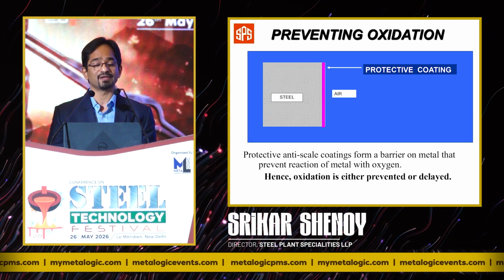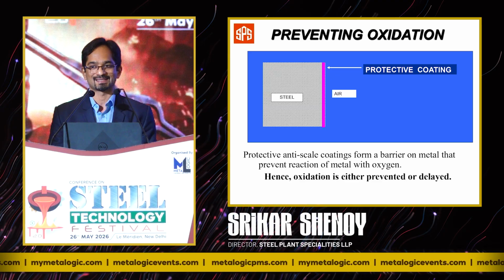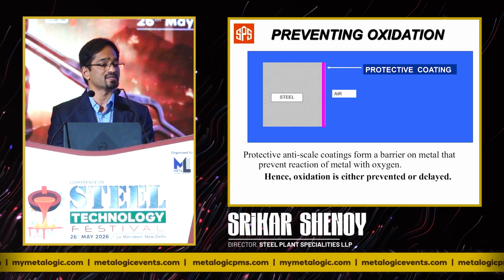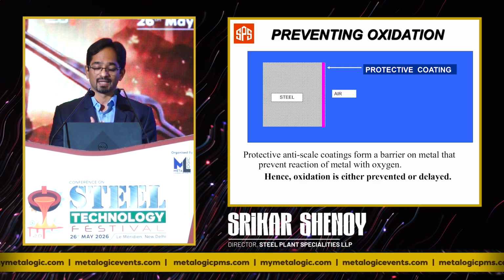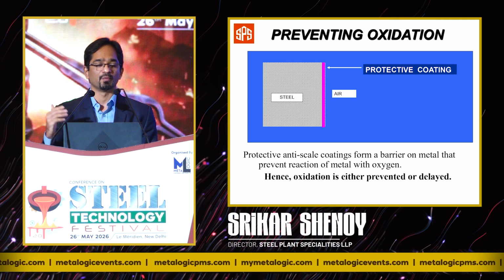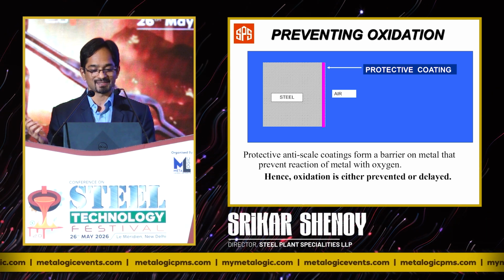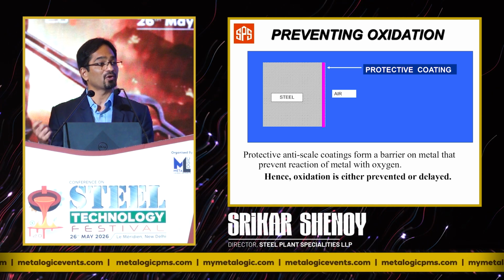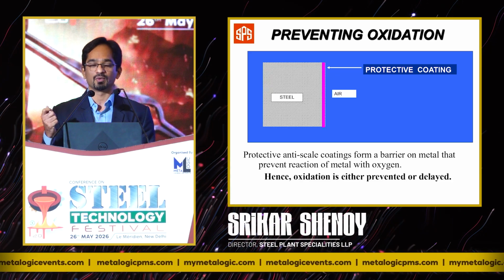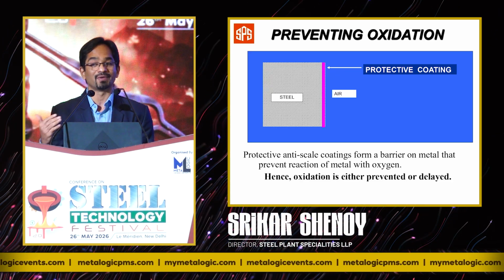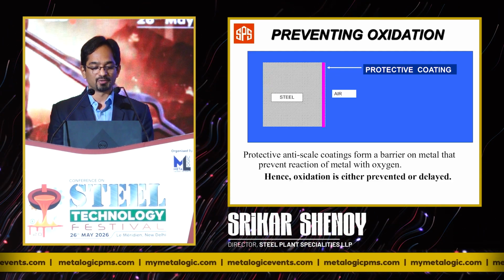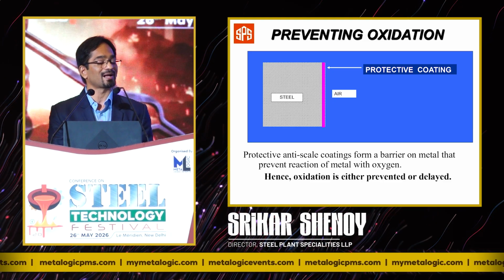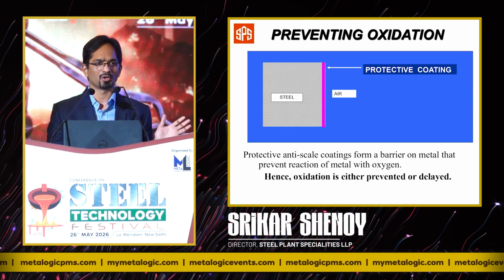What I mean to say is, if the temperature is 1000 degrees or less, for example, in heat treatment operations, there are cases where we have been able to deliver zero scale loss. When it comes to 1250 degrees Celsius, there aren't many economical materials available to substantially reduce scaling. However, we have been able to reduce scale loss anywhere from 50% up to 80%, all documented.